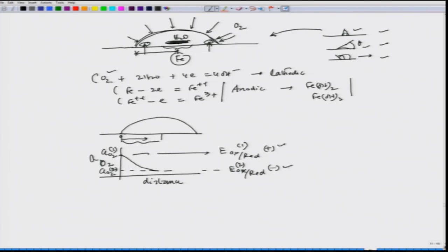So, this becomes positive, this becomes negative, or this becomes cathodic and this becomes anodic. So, finally, here we have anodic reaction and here we have cathodic reaction. And we must say that these are predominantly cathodic and here we have predominantly anodic reactions. Now, for the cathodic reactions, we can have cathodic reactions like this, but for that we have to have supply of oxygen or this OH minus should get decomposed and then form oxygen. But there are two more strong oxidation reactions, which are these two.